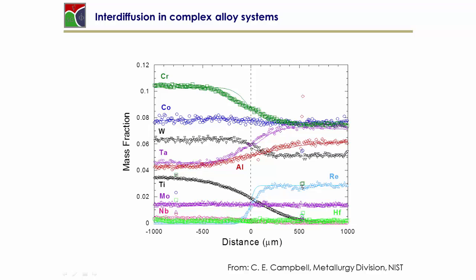Here is an example for such kind of DICTRA simulation. And what you see here is a diffusion couple of two different superalloys mentioned up here, which have been brought into contact at this line at time zero, and then they have been kept at 1293 centigrade for 100 hours.